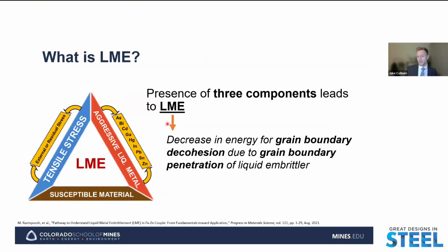And so with LME, we can define that as the decrease in energy for grain boundary decohesion due to grain boundary penetration of a liquid embrittler. So essentially, a normally ductile material is going to behave in a brittle fashion. And that brittle behavior is what leads to the crack formation that we see in these welds. While there are a number of binary LME couples that we could be concerned with, the one we're going to be looking at for galvanized third generation advanced high strength steels is the zinc iron LME couple.